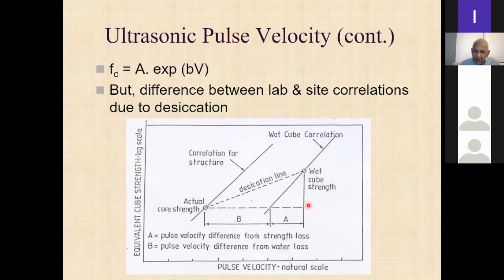But separately, if you do a lab correlation, you will get something like that. And this loss is the pulse velocity difference from the strength loss. In other words, this is the lab value, and this is the strength in the structure. So that pulse velocity loss is because of the change in strength.